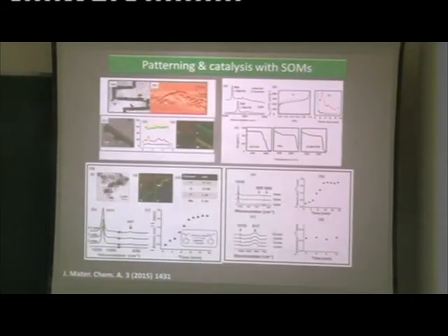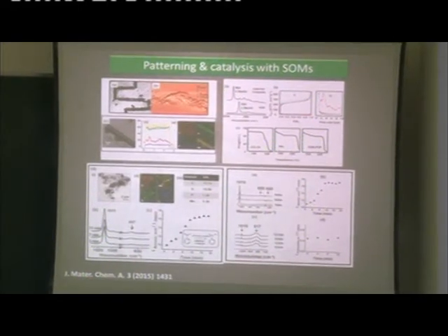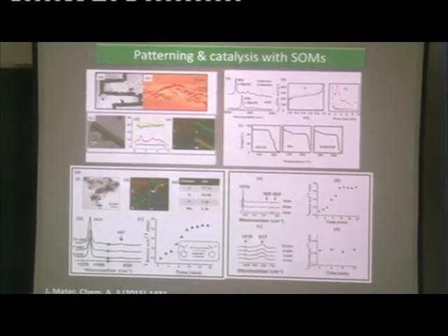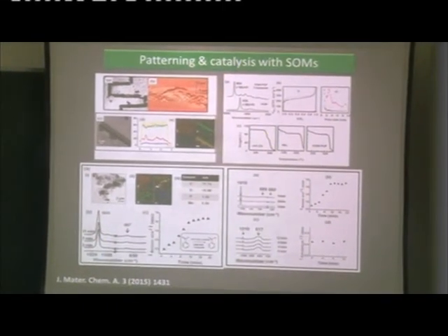So what we found is that we are able to form these types of patterns, and we did line scans with transmission electron microscopy. Now what is a line scan in transmission electron microscopy? When you have a small particle like a nanoparticle and you view it with a transmission electron microscope, because of the impingement of the electron beam on your material, you have emission of the corresponding X-rays because of the excitation of the electrons from one shell of the element to the other shell.